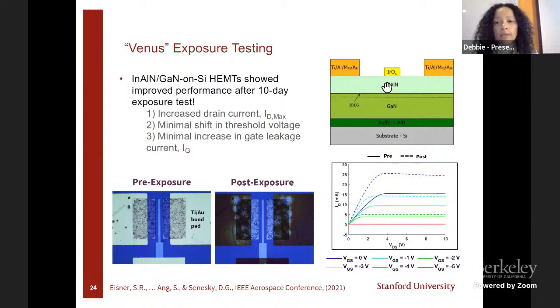Well, the gate material matters because you want a Schottky contact, right? Unfortunately, you can create a metal insulator structure. We've done that. A lot of the metallizations just sink into this top layer, which can degrade. And so we want a high temperature version of a Schottky contact. We've probably studied most of them in the group. Some of them just flat out evaporate, like molybdenum, for example, they just disappear after time. So a lot of tricks in, like, do we passivate it? Do we need an MIS structure? Things like that. And then the ohmic contacts as well, a lot of art goes into this. And so still lots of work to be done here.